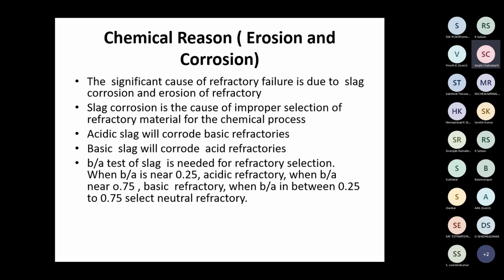Acidic slag will attack basic refractory, and basic slag will attack acid refractories. So there is a test for that. B by A is the basicity by acidity. A test of slag is needed for refractory selection, where B is CaO and A is silica. So it is calcium oxide divided by silica. These are the ratios, and this ratio is needed for refractory selection.